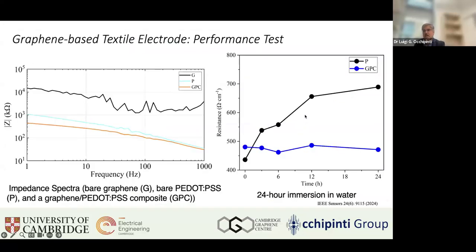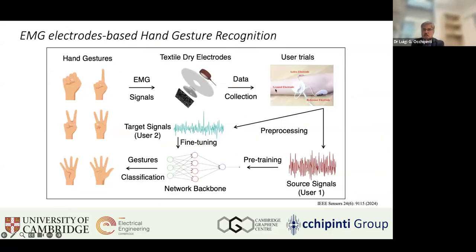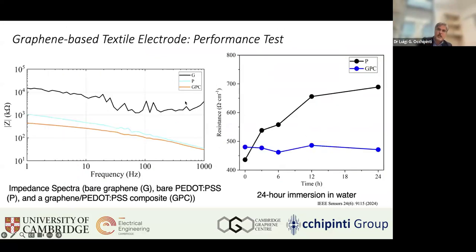And we tested this in, okay, let me show you the next slide. We tested this in a typical configuration for EMG electrodes, with 3 electrodes, all starting from commercially available electrodes, removing the wet gel part, and replacing it with our textile dry electrodes. In this slide, you can see a comparison of a graphene-only electrode without PEDOT:PSS, the PEDOT:PSS-only electrode, which is known for low impedance with skin as a conductive polymer, and then the combined graphene and PEDOT:PSS electrode, which achieves the lowest impedance in the frequency range typically used for EMG.